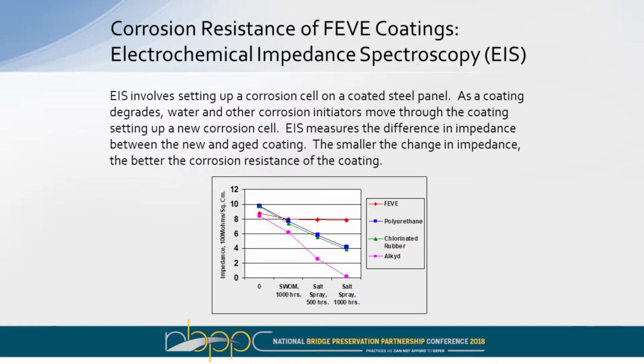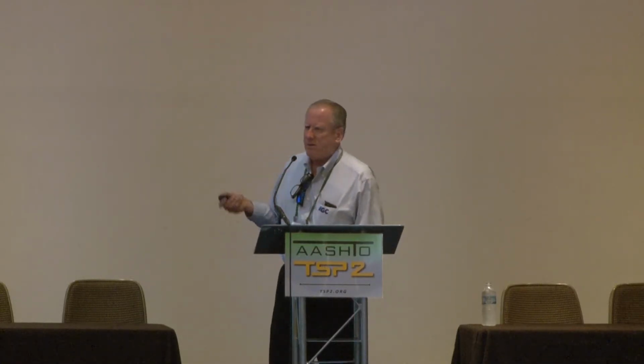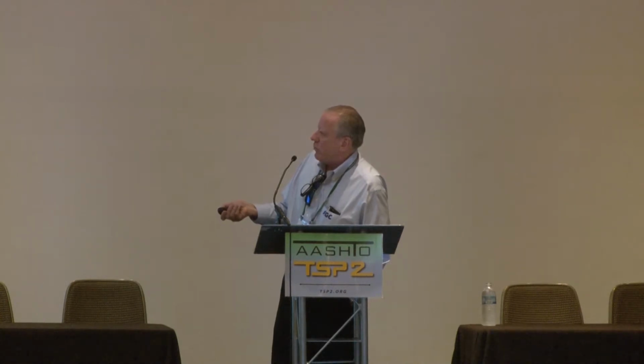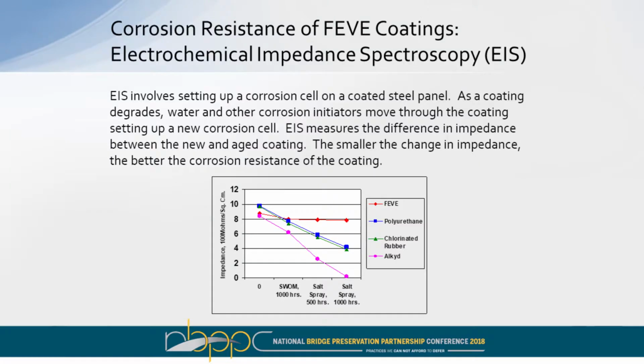And basically, as the chloride, water, and oxygen move through the film, you set up new corrosion cells, and you're really measuring the difference in impedance between those. And in this particular test, to top everything off, what they've done is they've put it in the SWOM, which is an accelerated weathering test. So again, they've measured impedance at various points along the way. And again, the flatter the line, the less change in impedance, the better the protection the coating is going to